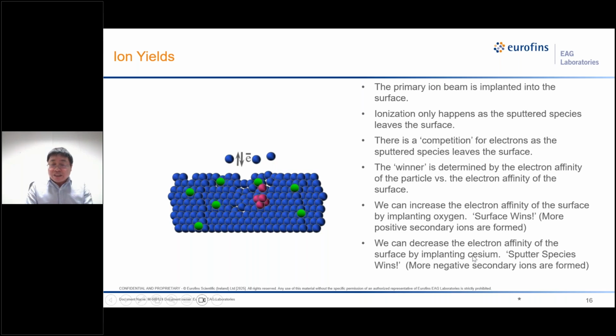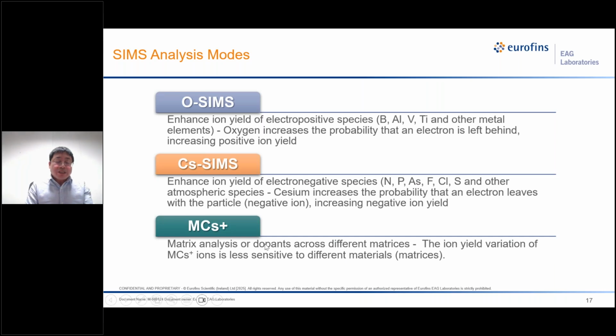Or we can decrease the electron affinity of the surface by implanting cesium, because cesium has more electrons, and then it favors the negative secondary ion formation. To summarize, the oxygen source was used to enhance the ion yield of electropositive species. In this case, boron, aluminum, vanadium, titanium, and other metals are analyzed with oxygen beam. Cesium beam enhances ion yield of electronegative species, for example, nitrogen, phosphorus, arsenic, fluorine, chlorine, sulfur, and other atmospheric species are analyzed with cesium beam.